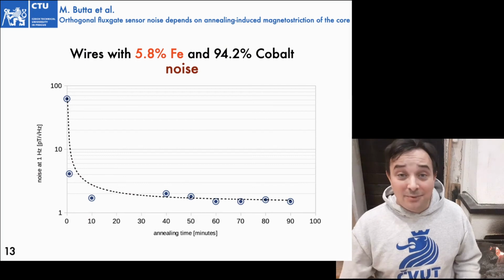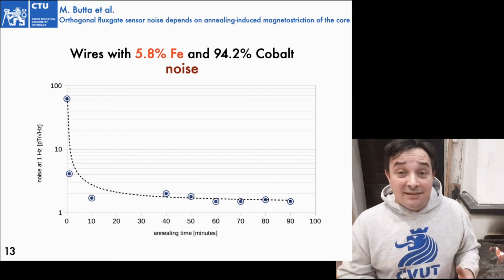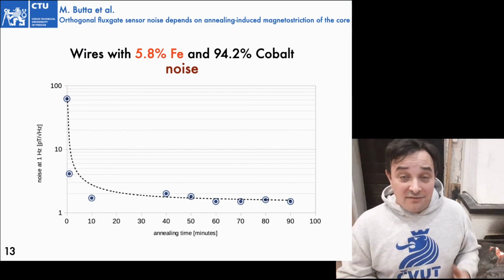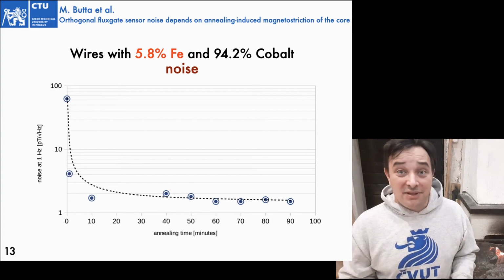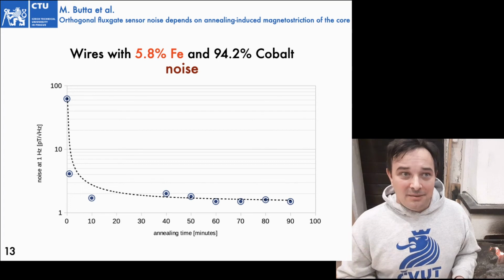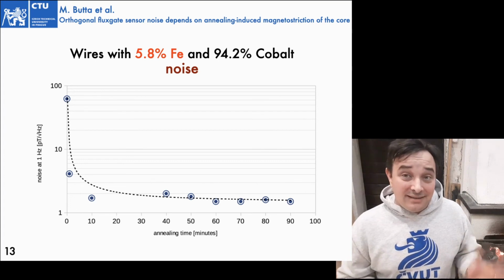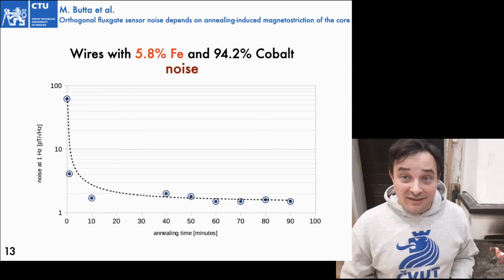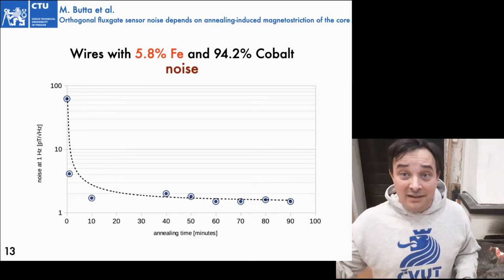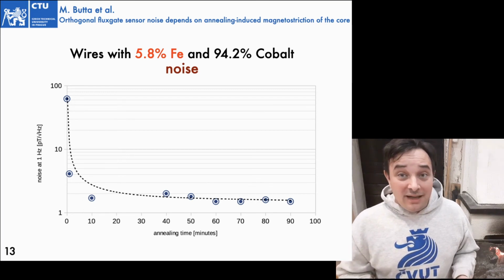And that's actually what happens. As you can see in this graph, the noise for as-cast wires is very large. It's about 60 picotesla per root hertz at 1 hertz, which is very large noise. But then, when I increase the annealing time, the noise just decreases. And it doesn't rise back when I anneal for a longer time. In fact, for 1 hour annealing, I go down to 1.5 picotesla per root hertz.